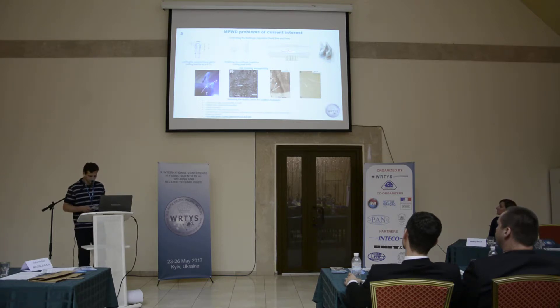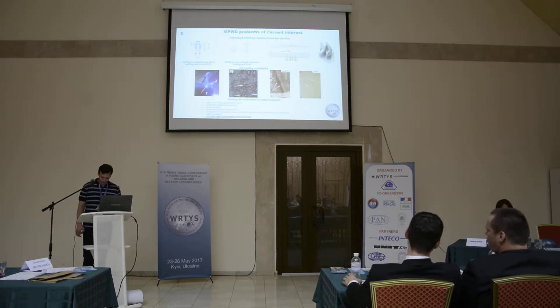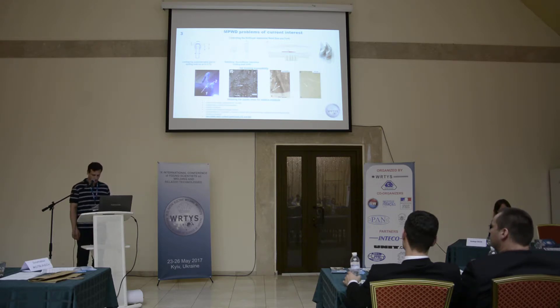The second major problem is that nickel superalloys are prone to micro and macro cracking in both fusion welding and in the subsequent post-weld heat treatment. A crucial characteristic responsible for such welded joint technological strength is heat input in the process.